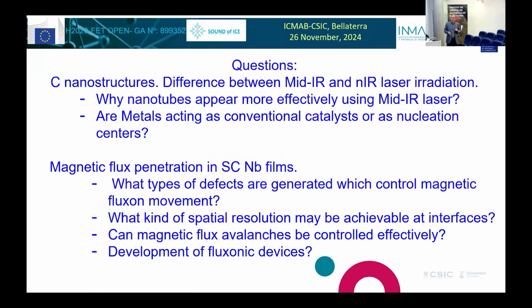But now let me give you some questions to finish. Regarding the carbon nanostructures, we found out that in the mid-IR at 10.6 microns, what we get is single wall carbon nanotubes. But when we go to the near IR laser at 1 micron wavelength, we never get that unless we put some type of, let's say, transition metal with rare earth metal and with a lot of work. It's very difficult to get it. With the CO2 laser, they come out readily and naturally. The question is if the metals are acting as conventional catalysts or as nucleation centers.